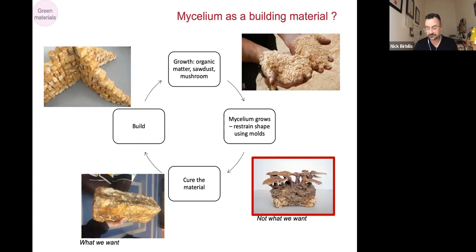So here's a bit of a workflow of how something like this might work. And one can conceive of composting waste food as the organic matter food source for mycelium growth. So think about that, half eaten slice of pizza or your leftover bread. And that can enter the growth cycle for mycelium to produce bricks. The bricks, basically in a mold or briquettes, whatever shapes you want, they grow in a mold and they can have their growth terminated by slight exposure to elevated temperatures. Not very hot, I'm talking about 60 to 80 Celsius for a flash curing.